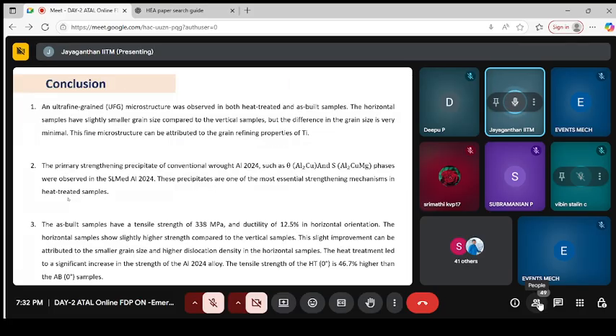And again, to conclude, we are able to produce an ultra fine grained microstructure by using titanium modified aluminum 2024 alloy through 3D printing. We are able to prove it provides better tensile and fatigue properties as compared to conventionally produced aluminum alloy. Having established properties, we have done virtual prototyping of an engine mounting bracket for aircraft application with a significant weight reduction without compromising properties. Rather, we were able to improve static as well as dynamic properties.